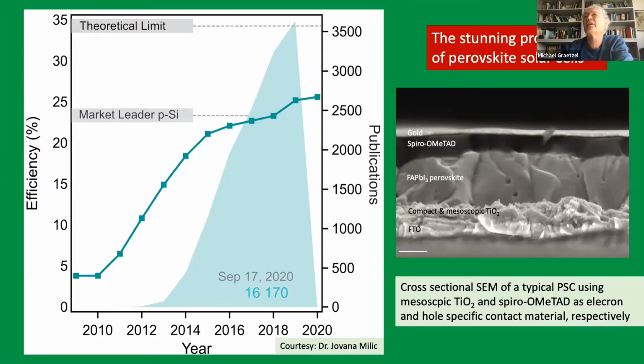In other words, a contact that selectively collects positive charges, and then you need some kind of back collector, which is gold. That could be carbon. There are many options, and all this is only about 1 micron maximum thick. Compare this to a silicon cell that is 250 microns thick. So you use 250 times less material. And this can be made by solution processing at low temperatures, and you get over 25%, which beats polycrystalline silicon, not the crystalline yet. Crystalline silicon record is 26.7%, but the polycrystalline is already beaten, and there are some new results where over 26% have been reached, but not certified yet.